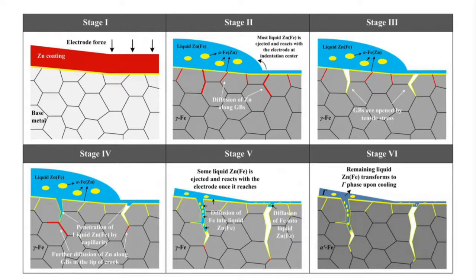In step 3, we could see that the grain boundaries are open due to the tensile stress. And moving on to stage 4, the penetration of the liquid metal will continue by capillarity and cause further cracking. So we can see for stage 5, the cracking still continues, and the liquid metal atoms, when absorbed on a susceptible metal, will reduce the metal bond strength within the grain boundary regions of the susceptible metal. In the end, it will result in adsorption-induced cracking.